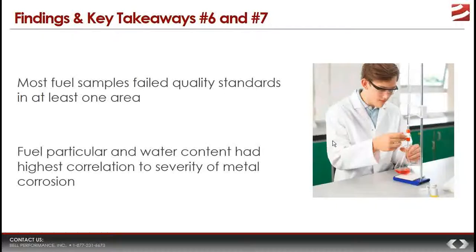Takeaways number 6 and 7 concerned what they found when they tested the characteristics of the fuel samples. The interesting thing they found is when they tested the fuel samples according to the specifications, the ASTM specifications for diesel fuel, they found that virtually all of them failed the ASTM spec in one area or the other. The most common area that they failed was in water and particulate content. And that matters because the seventh takeaway they found was that failing water and particulate content tests had the highest correlation to having severe corrosion in storage tanks.